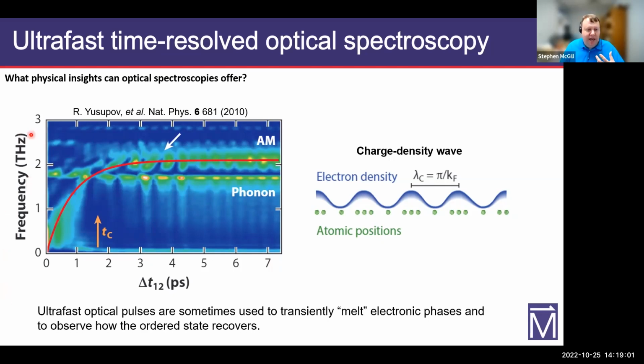And so what happens is we can see that there is an amplitude mode of the charge density wave just above 2 terahertz. There's also a phonon mode that exists just below 2 terahertz. Initially, the amplitude mode of that charge density wave, which is here and seems to recover out around 6 picoseconds, is destroyed. It's melted right at 0 time when that excitation pulse comes in. And then we can watch the intermediate states as that recovers. Here, for example, there are some odd line shapes happening where it's sort of asymmetrical and diagonal.